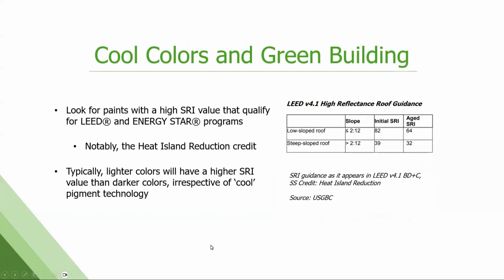So a lot of you are probably much more familiar with LEED than I am. I know enough to be dangerous, but 4.1 for low slope, it needs to have an initial SRI value of 82. Those are whites, right? We can't get to 80 plus or even 75 plus SRI with anything but whites. So low slope is white. Steep slope, however, at 39 initial SRI, there's quite a few mid-tone colors that will meet that without an issue.